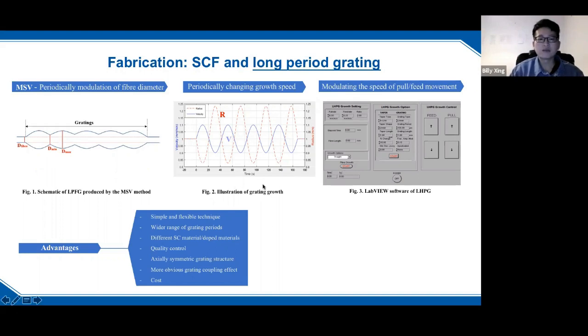This is a MATLAB illustration of the grating growth, and we use LabVIEW software to control our laser-heated pedestal growth procedure. The advantage of this technique over the previous dicing method is that it is a very simple and flexible technique, and we can grow a large range of grating periods, since the period of the grating is not limited by the blade thickness.